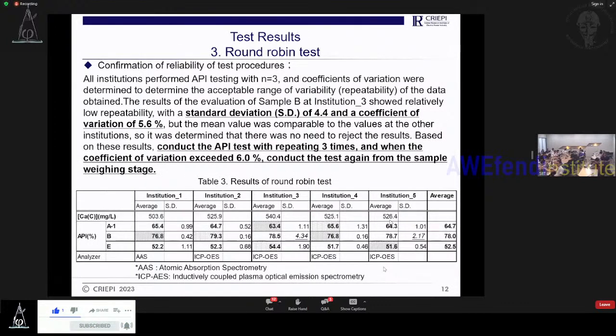The next figure shows the result from the data. We operated a round-robin test with 5 institutions. I delivered 3 fly ash samples named A1, B, and E. The upper row shows the CAC, the concentration of calcium ion in the standard specimen, standard line. From this data, all institutions have the same result.